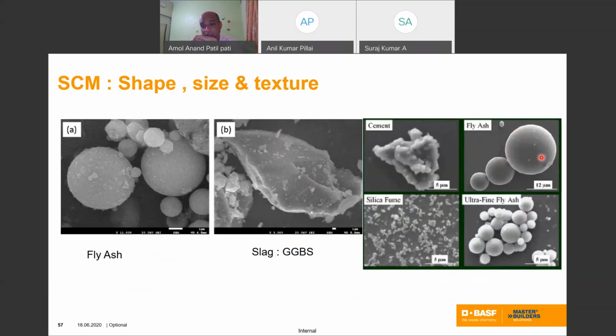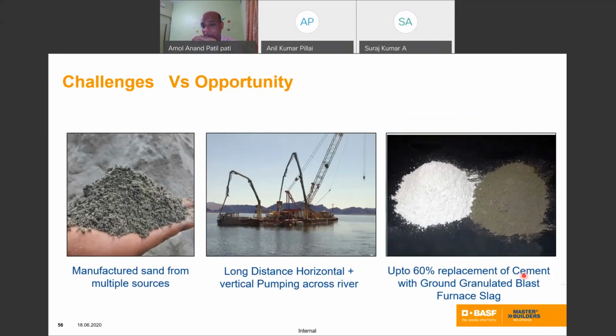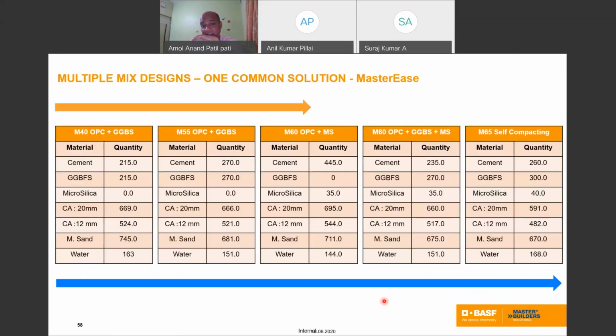So fly ash gives water reduction in the mix, increases workability, increases the slump, and increases the flow of the concrete mix. But when we use a high amount of fly ash, the mix becomes sticky, because this is an inherent property of fly ash, because of the size, shape, and texture of the fly ash particles. So all these issues arise in these projects designed with high replacement of cement. Again, these are the basic challenges that they have.